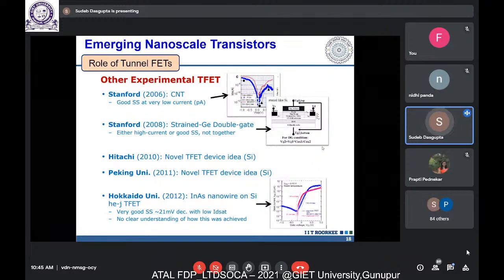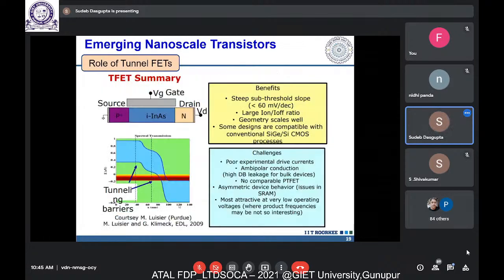Don't worry about what this nanowire is all about, but the base material was indium arsenide, and the result was very important and interesting. They received a subthreshold slope of 20 millivolts per decade. So your switching speeds are very fast in this case. So you can use it for all high frequency applications, wherever your switching speeds are very high, right? And that is where you need to put your next efforts as far as tunnel FET is concerned.